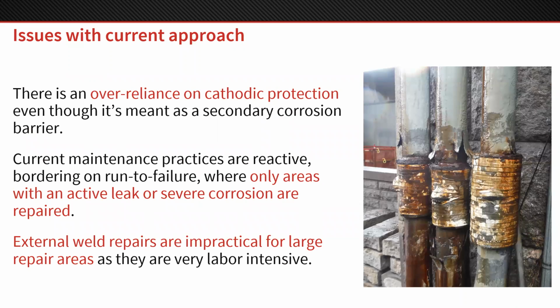So it sounds simple enough, but there are some issues with our current approach to repairing pipe type cables. The biggest thing is that we're really relying on the cathodic protection of these systems because so many of them are operating with coatings past their service life. Cathodic protection is great as a secondary corrosion barrier, but as more and more failures happen on your protective coating, it's going to overwhelm the cathodic protection and you're going to get corrosion regardless.